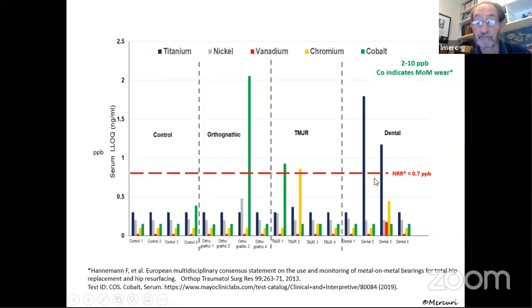The interesting one was the dental implants. So this is our dental implant group. Their titanium levels were very high, well over the normal reference range. And that makes sense because when you put a dental implant in, it's under load all the time. So you would expect ions, titanium ions, to come off. Now, do titanium ions cause a problem?